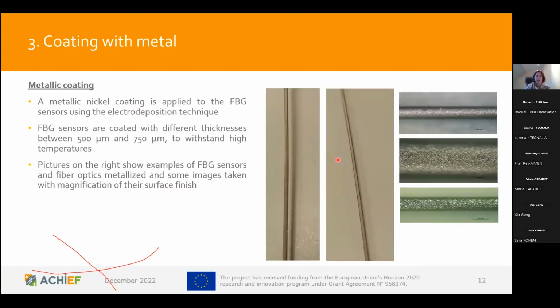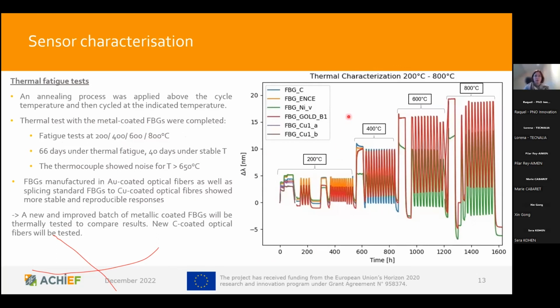So they went ahead with nickel and nicely were able to also deposit different thicknesses, 500 and 750 micrometers, of metal coating around the sensor. Again, we were curious if the sensors actually continued to perform well, and exposed them to a thermal fatigue test. That means cycling the temperature over an extended amount of time. You see here, for 2 months, we cycled them at intervals between 200 and 800 degrees Celsius and observed if the wavelength shift nicely follows this temperature cycling. And you see here overlaid different metallic coated fibers for comparison.